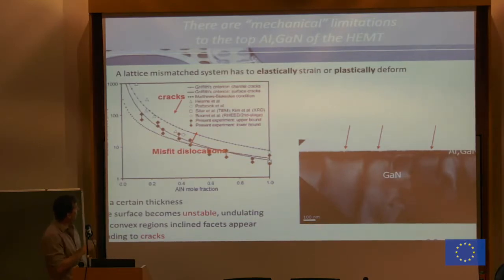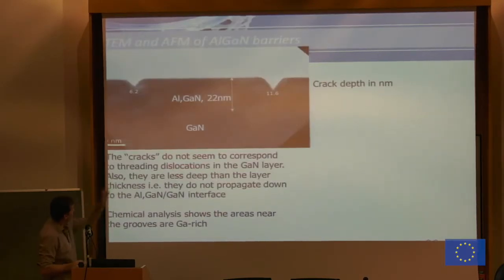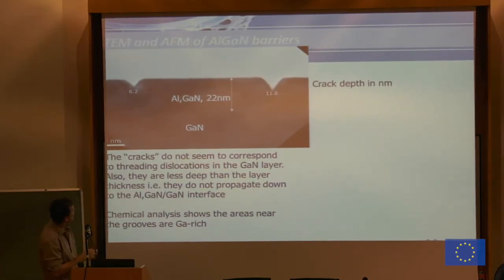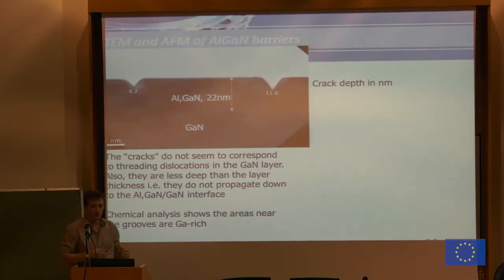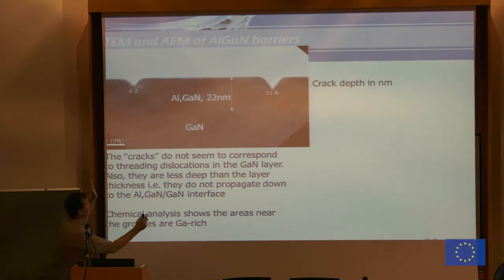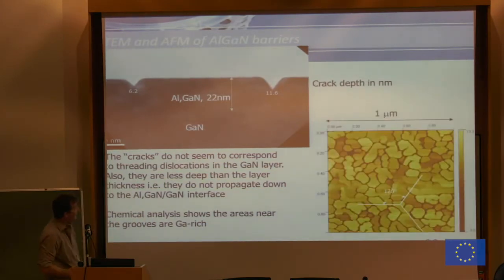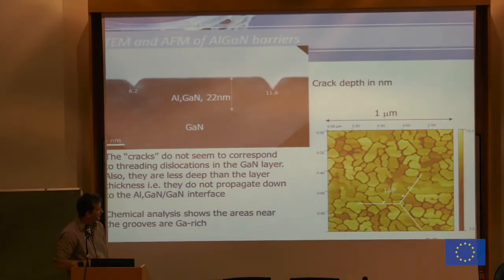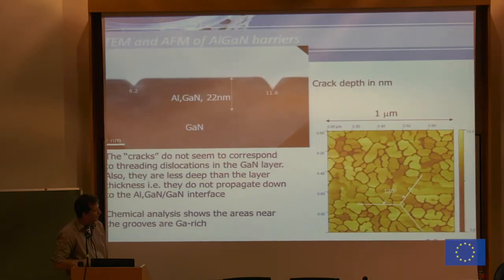Now what you can see, as we have shown in this critical thickness plot before, is that the way the AlGaN relaxes in this configuration is not by misfit dislocations, but by the formation of these grooves in the surface. If you look at a close-up of that, the interface is not very visible here, but here is the gallium nitride, and then here starts the AlGaN. The relaxation of this AlGaN that is under tensile strain is really the formation of grooves, so you can see that the stress of the AlGaN that is being pulled is relaxing by these forms. This is a top view AFM of the same picture, so you can see that these grooves even preferentially follow the crystal orientations of your Wurtzite crystal.